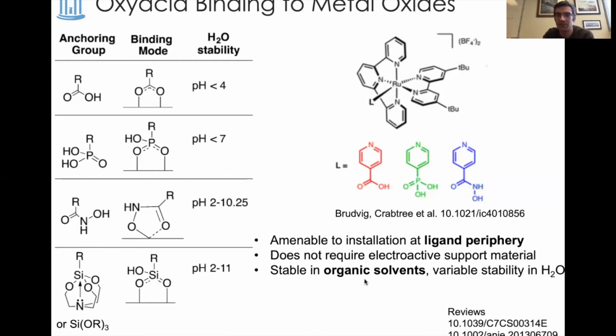Oftentimes in organic solvents, these linkages can be very strong and stable for days or weeks. In water, stability is the big knock on oxyacid linkers. So an example is that carboxylates will bind to something like titanium dioxide pretty well at pH 1, but as the pH goes above about 4, you get hydrolysis and desorption from the surface. Phosphonic acid derivatives bind better up to about neutral pH, and hydroxamic acids and silanes tend to have better stability under basic conditions.